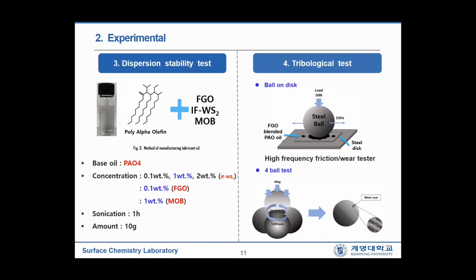Each of the FGO-dispersed PAO oils was applied between a steel ball and a steel disc in reciprocating ball-on-disc mode. A 10 Hz reciprocation frequency was applied with 50 newtons of load for 360 seconds. We have also performed 4-ball tests like this.